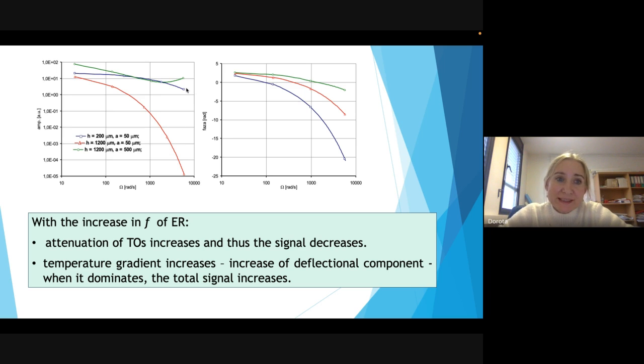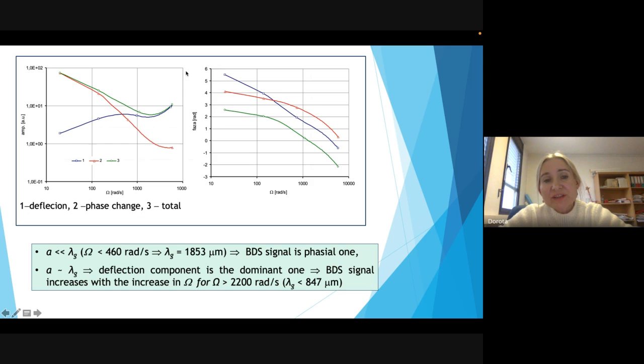What for wide probe beams, the beams with high radius, the deflectional component, the component that results from the beam deflection, increases. So it may result in the increase of the total measured signal. Yeah. To see if it's really like that, let's see the total signal and both components: that one that is caused by deflection, and that one that is caused by the phase change.